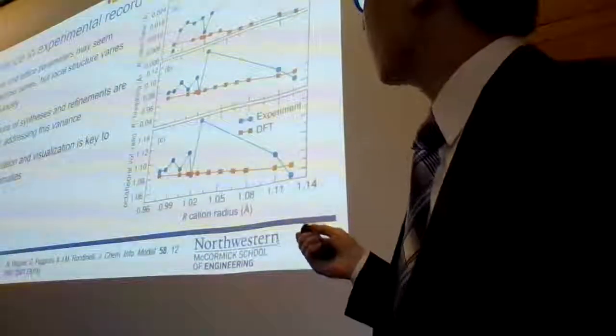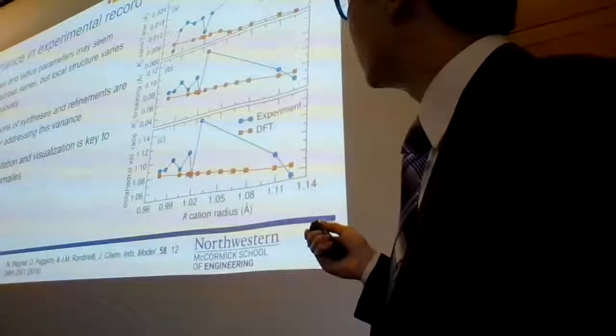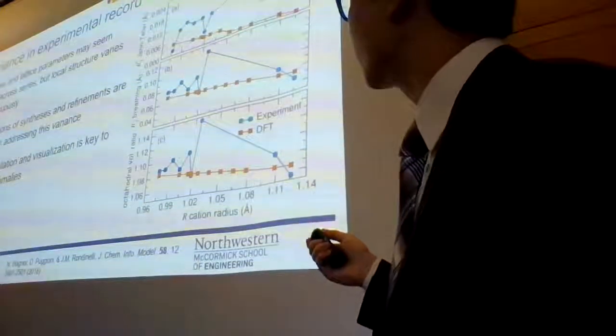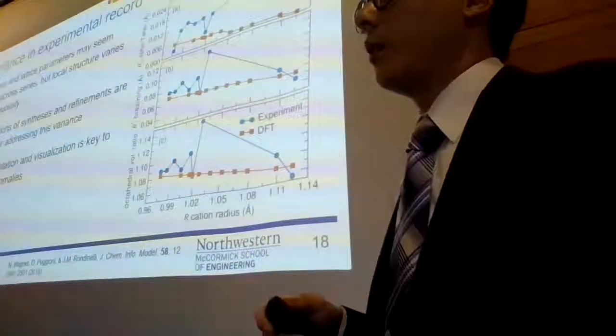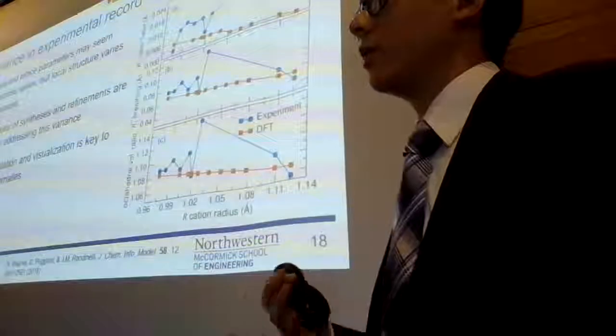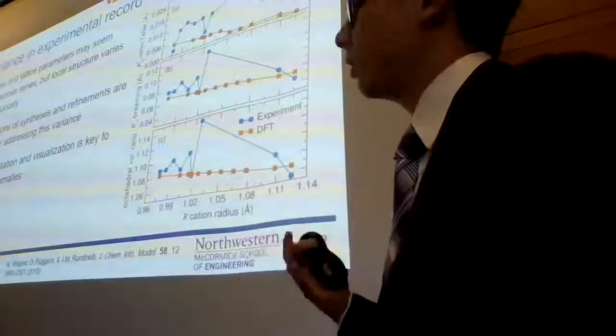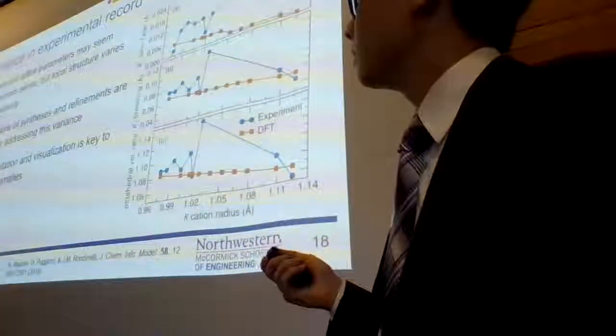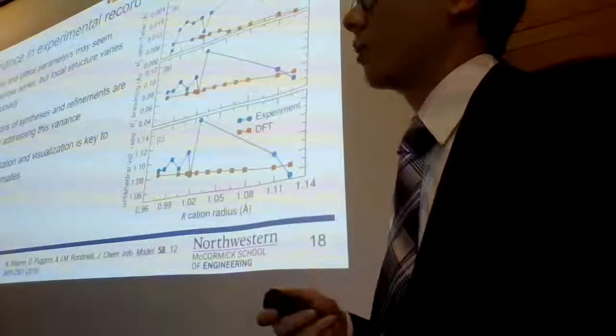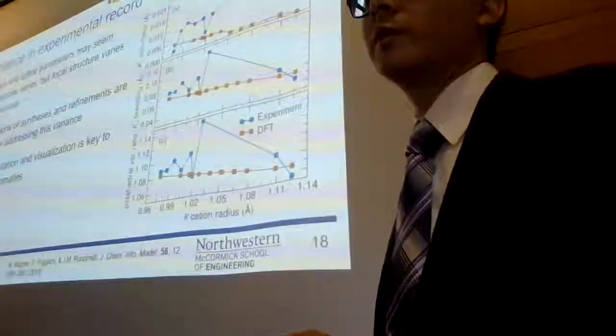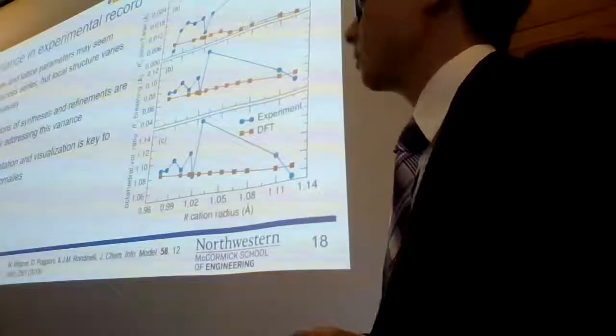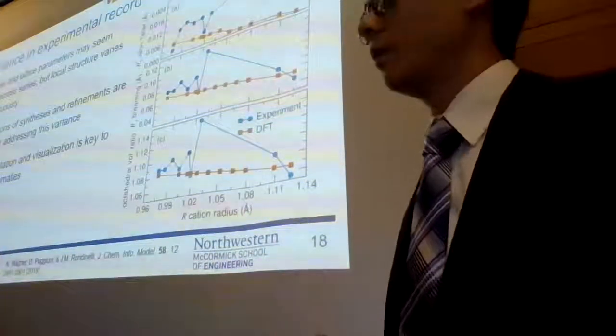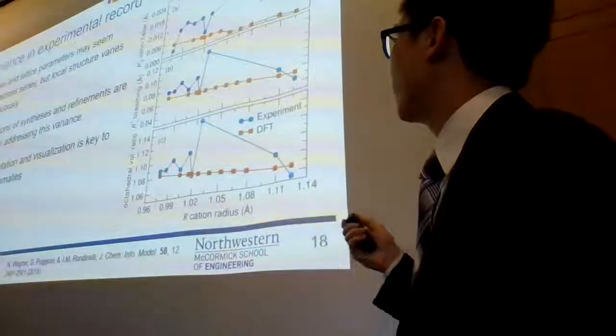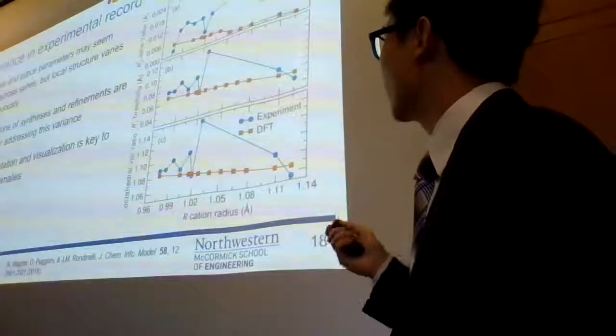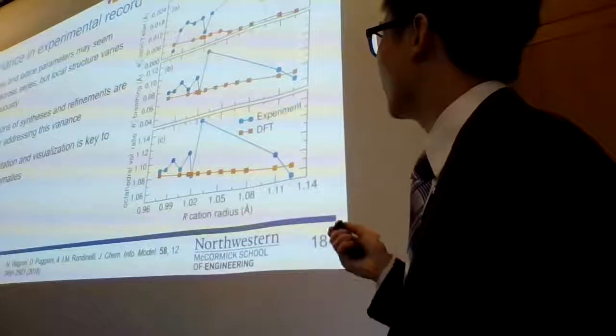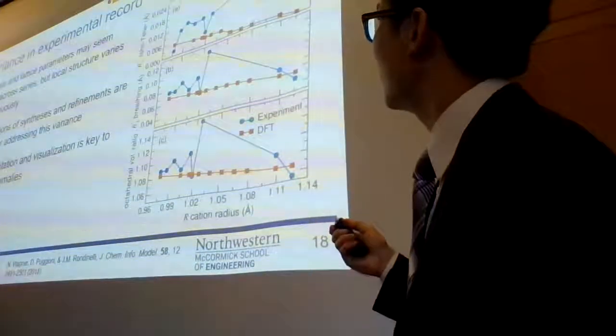But unfortunately, the experimental amplitudes of these breathing and Jahn-Teller modes oscillate dramatically. That's because even though these refinements are published with pretty good R values, such that the lattice parameters and volumes agree sensibly across the series, the very small local distortions vary depending on the refinement. And as a result, if you were to do a linear regression here and plot a line through,